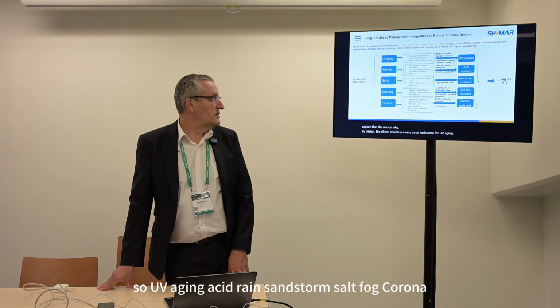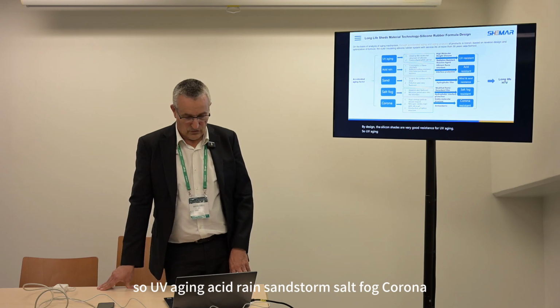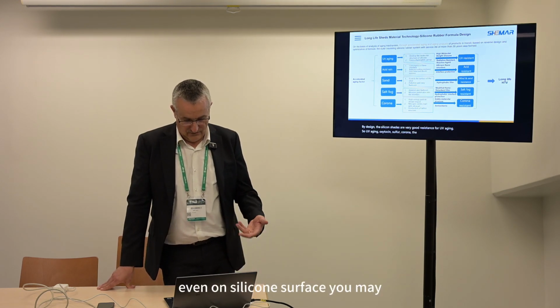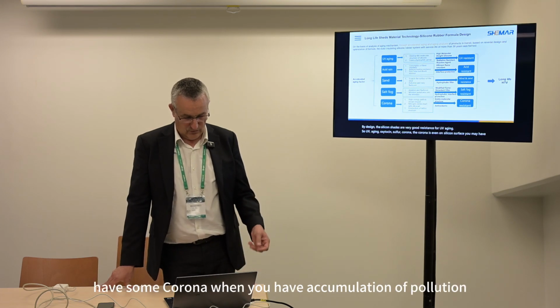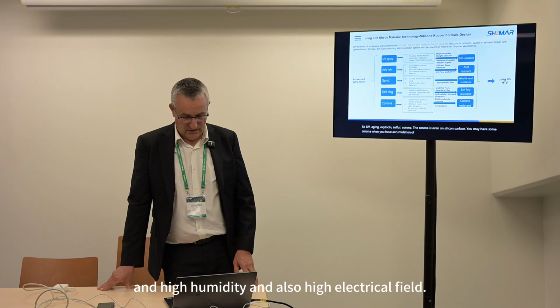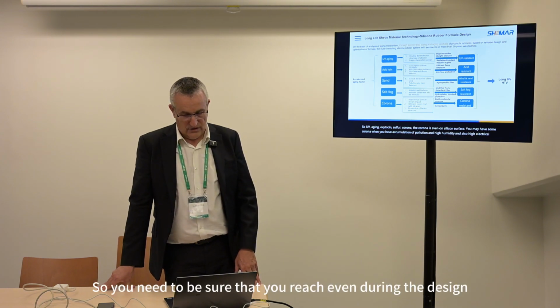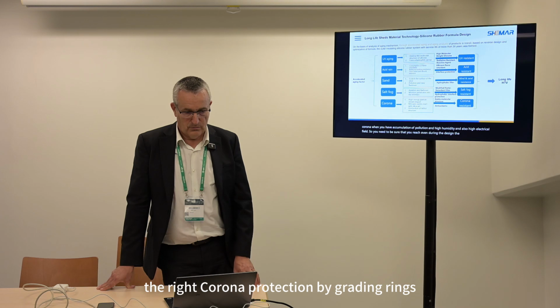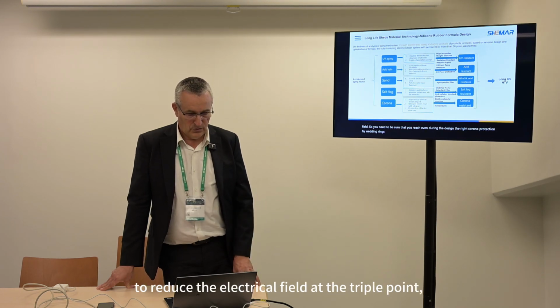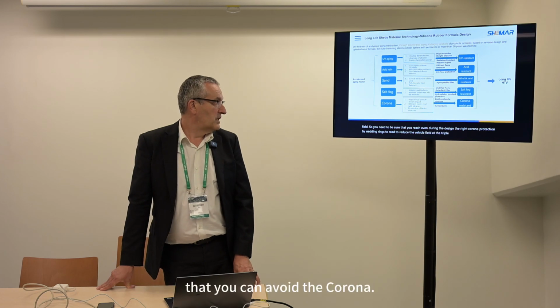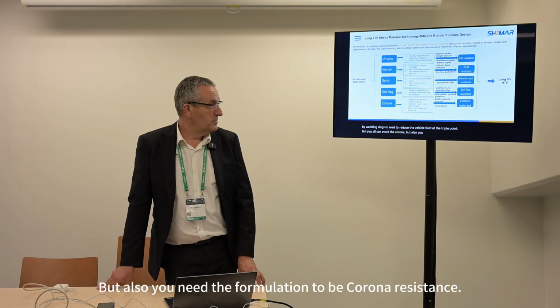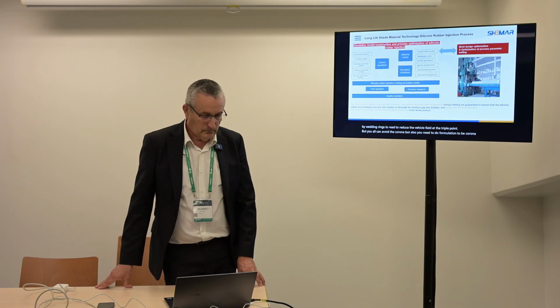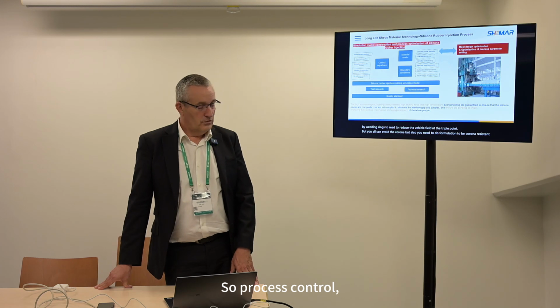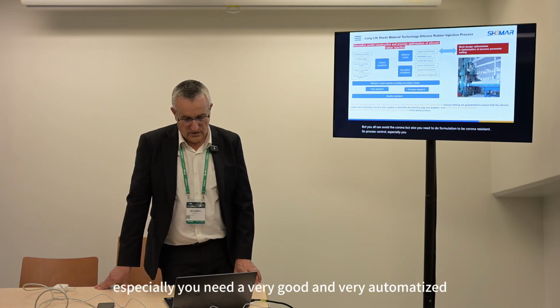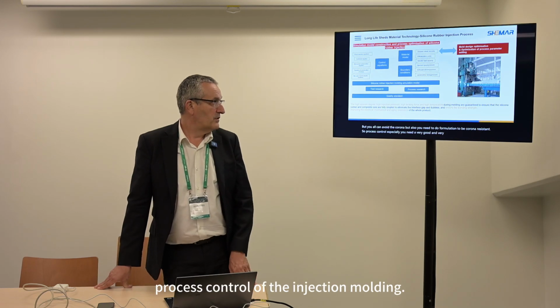UV aging, acid rain, sandstorm, salt fog, corona. Even on a silicone surface, you may have some corona when you have accumulation of pollution, high humidity and also a high electrical field. So you need to be sure, even during the design, that you reach the right corona protection by the grading rings to reduce the electrical field at the triple point, so that you can avoid the corona, but you also need the formulation to be corona resistant. So process control: you need a very good and very automatized process control of the injection molding.